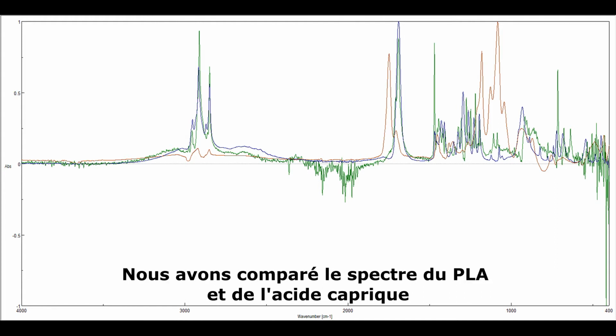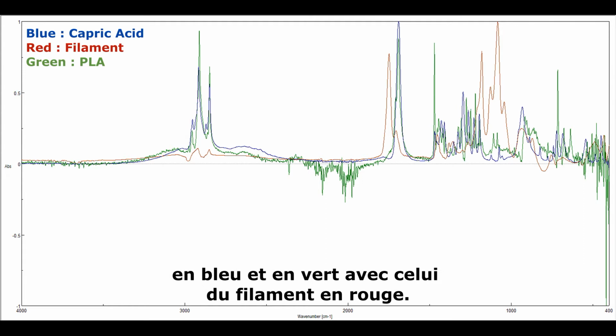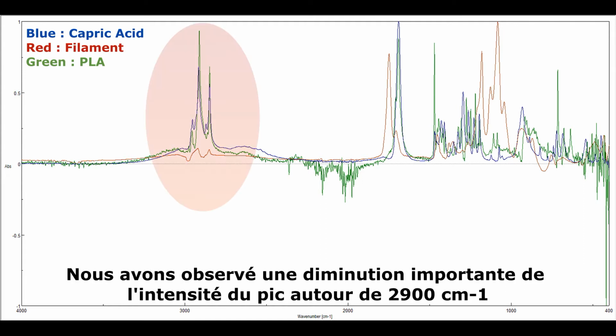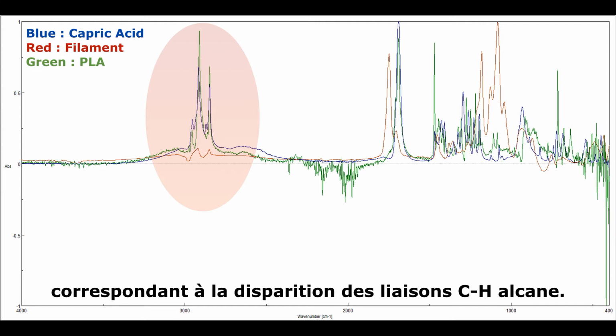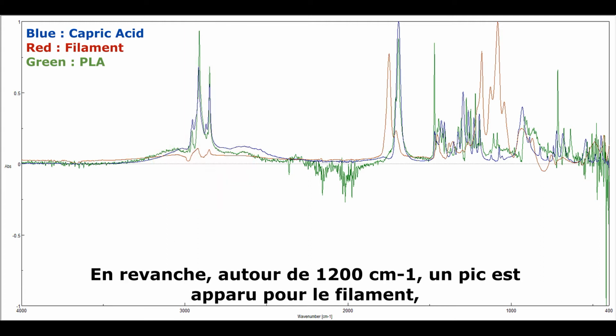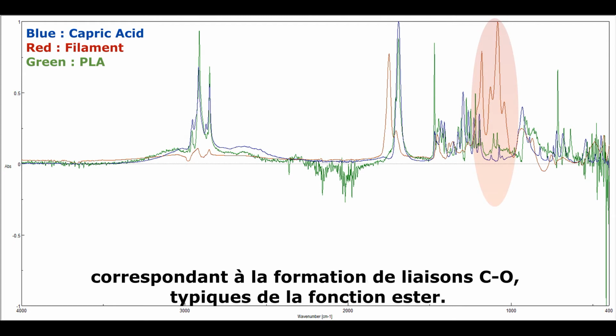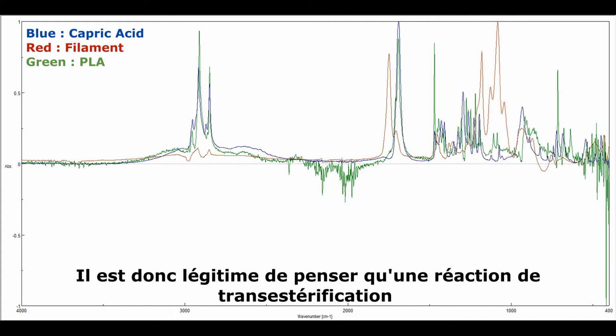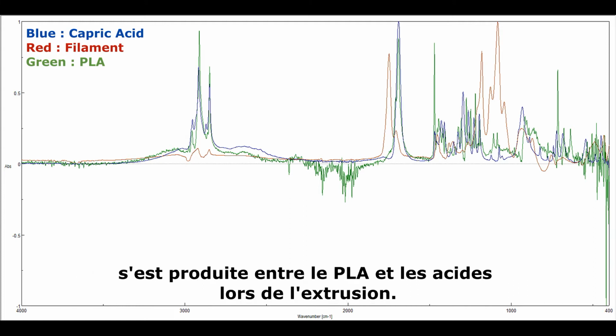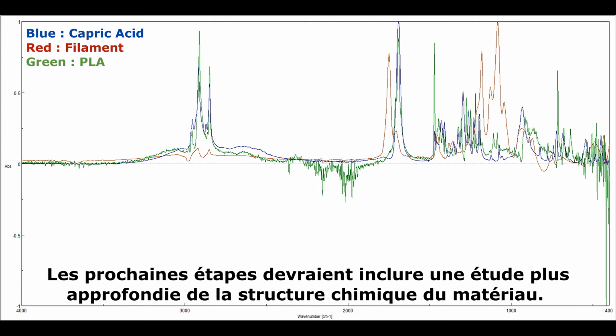We compared the PLA and capric acid spectrum in blue and green with the filament in red. We observed an important decrease of the peak intensity around 2,900 cm^-1 for the filament, corresponding to the disappearance of CH alkane bonds. On the other hand, around 1,200 cm^-1, a peak appeared for the filament, corresponding to the formation of CO bonds, typical of the ester function. Therefore, it is legitimate to think that a reaction of transesterification happened between the PLA and the acids during the extrusion. Future studies should include further investigation of the material's chemical structure.